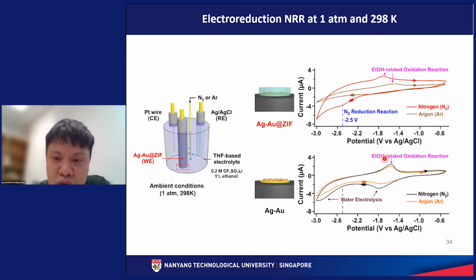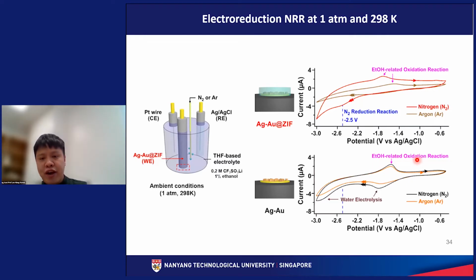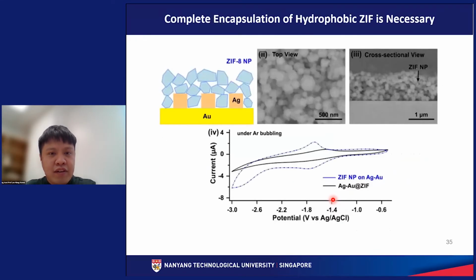Okay, so we also observe an anodic peak that is related to ethanol oxidation reaction. So furthermore, we also observe two water electrolysis peaks at around negative 1.8 volt, as well as around negative 2.8 volt. Okay, so I will go through them in detail later to explain why we identify this peak to be related to certain species.